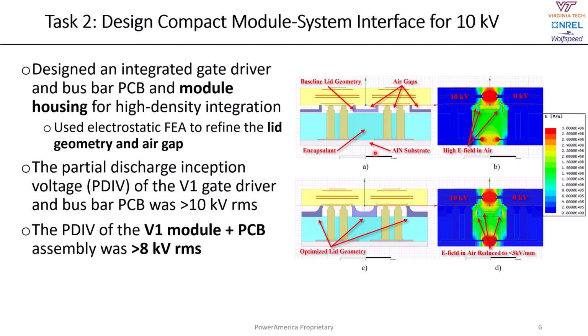So this is a 2D cross-section of the 10 kV module, where these are your spring terminals, the blue is the encapsulation, and the purple is the housing. And then we've identified here the air gaps that exist between the module and the PCB. As you can see from the electric field plot on the right, we have several areas where the peak electric field is getting close to the 3 megavolt per meter limit. By optimizing this lid together with the PCB, we're able to further reduce the electric field strength in that air gap.